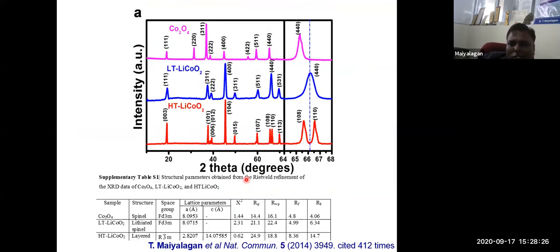So we confirm with the XRD the low temperature and high temperature spinel. You can see the cobalt oxide. Just say cobalt oxide, we just dope lithium inside the matrix. This is a spinel structure, and this is a layered structure. So you can see the difference in the XRD patterns, and you can do the refinement to fit the patterns of this lithium-doped low temperature spinel. This is a spinel structure, and this red one is a layered structure. You can see with the XRD and refinement to fit the parameters. So cobalt oxide also is a spinel structure, and